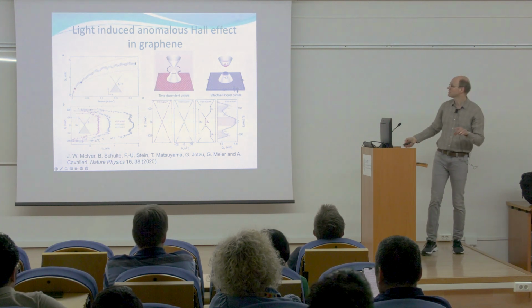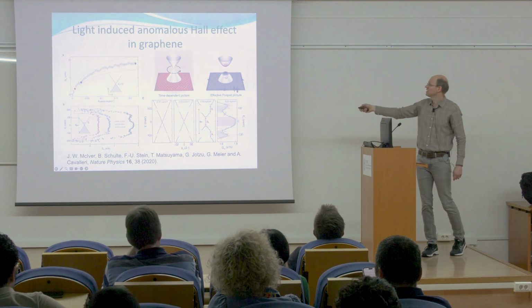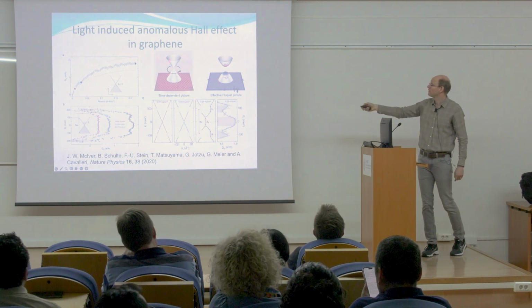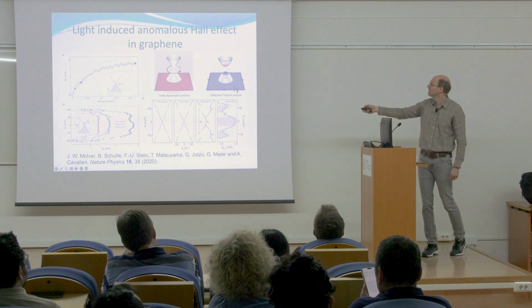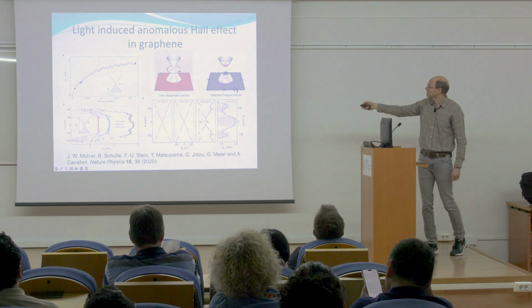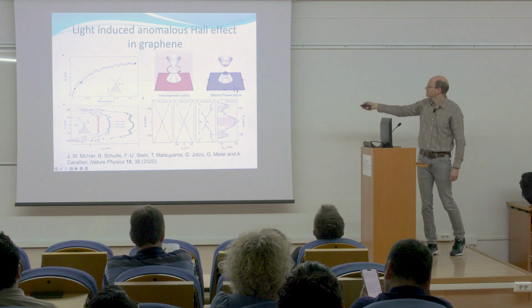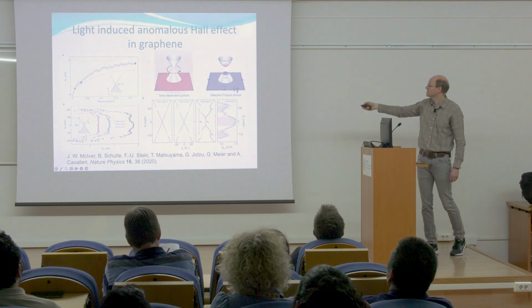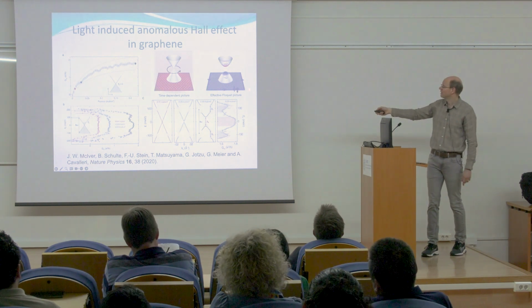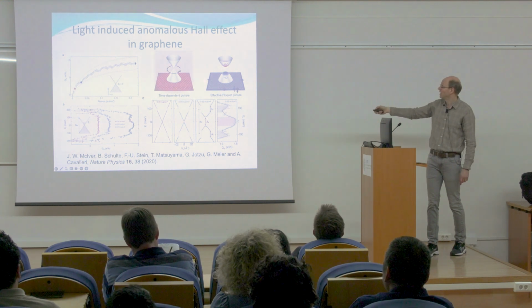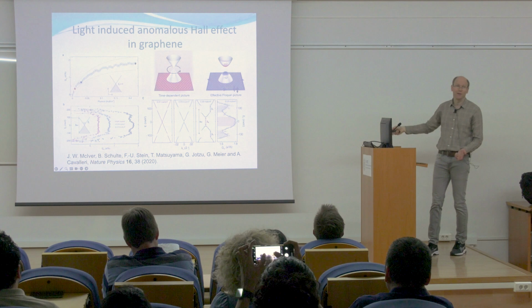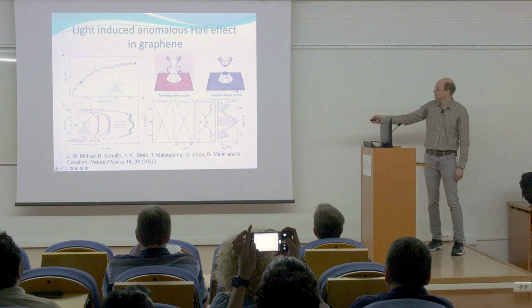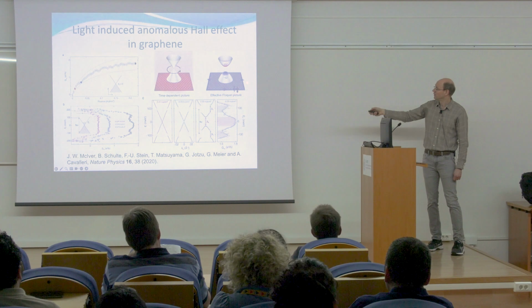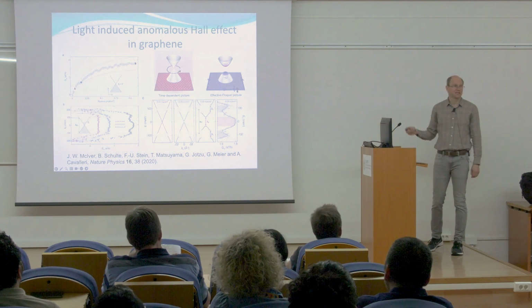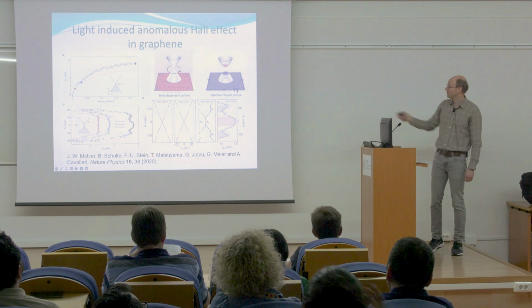You've changed the symmetries of the system, and it turns out that you can change the excitation spectrum, which has this Dirac-like feature in it. There's 2 Dirac cones in graphene. This is just focusing on one of them, but this linear crossing then becomes gapped. And so there's a finite energy to create an excitation in the system, and it turns out that there is a topological edge mode that appears, and you can measure the properties of this edge mode in an electrical transport and see that it follows more or less what is expected from the Floquet theory for such a system.